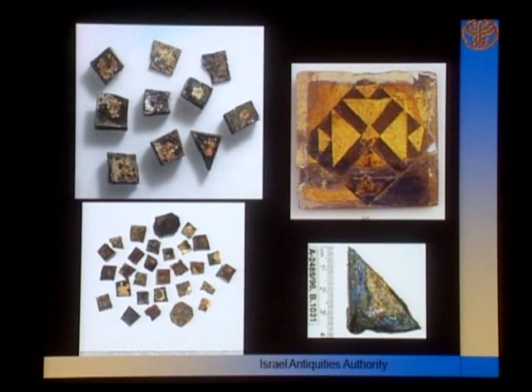However, gold glass was employed in the Byzantine period mostly for the making of small tesserae, which were used in wall mosaics. They were found together with colored glass tesserae in wide distribution, particularly in churches and chapels. Gold glass tiles were known from collections all over the world, but only recently were some unearthed in archaeological excavations. Here is a complete gold glass tile from the Israel Museum, Jerusalem, and a small fragment of such a tile excavated in the northern Galilee. Our research on the gold glass tiles helped us understand the production methods of the various elements in the gold glass panel from Caesarea.